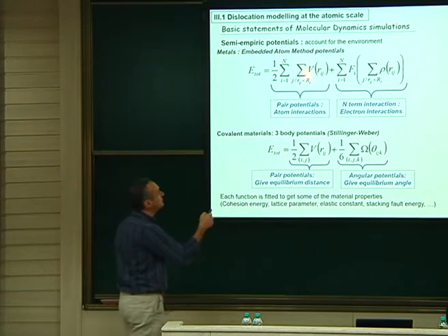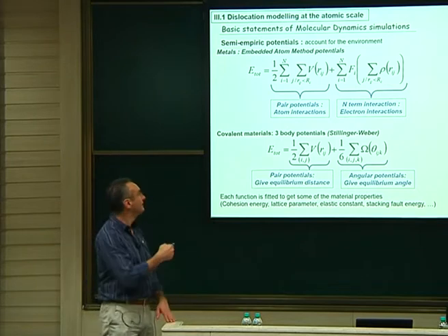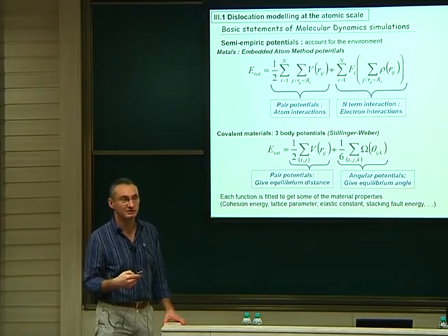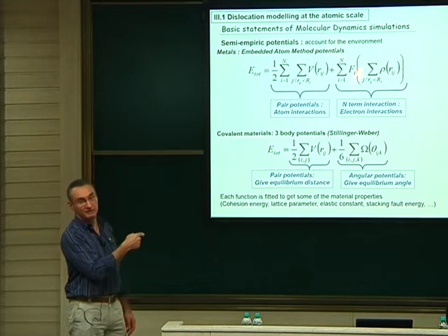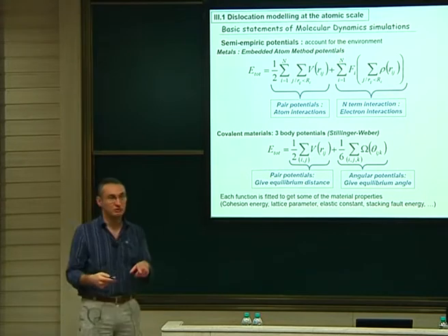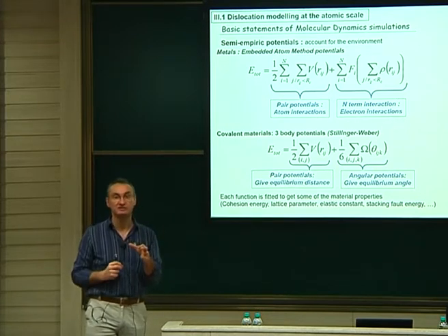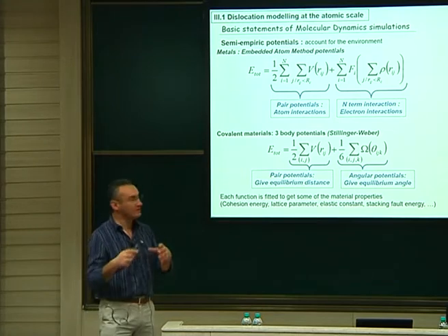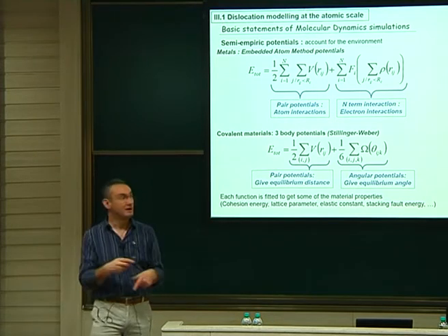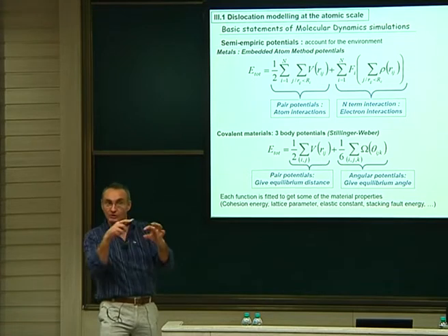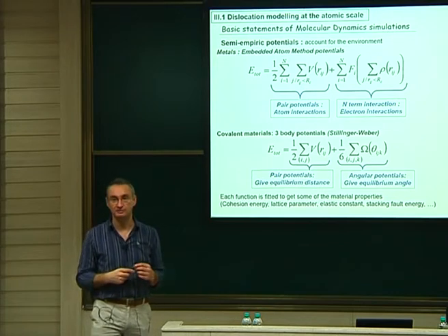How do you think we can compute the values for the parameters of the potentials typically? Do you know which model could give that? How can we compute V? DFT, exactly. This will be by density functional theory. So this is done by ab initio calculations. In ab initio calculations, they will have 100 atoms, no more, and they look how they interact. What is the energy if you put a vacancy inside? So they compute a vacancy energy, interstitial energy, and so on. They compute all these things, and they look at which potential they should put in order to get this. And this potential is now introduced in MD. So it's already a kind of multi-scale modeling. You do some ab initio, you identify these potentials that you use in MD.